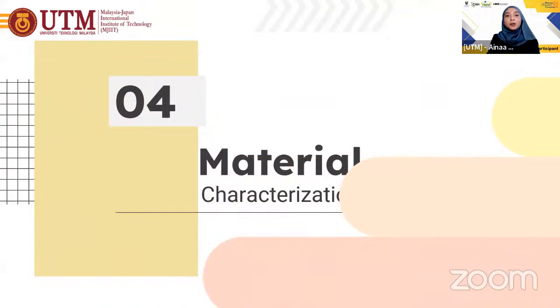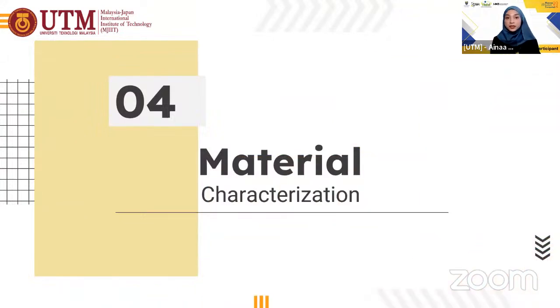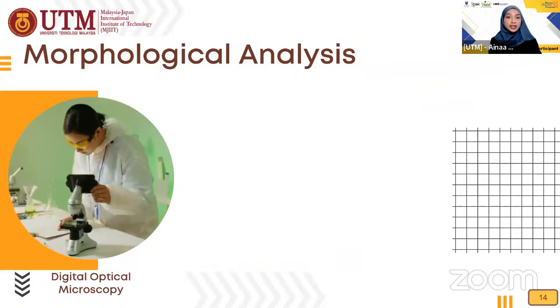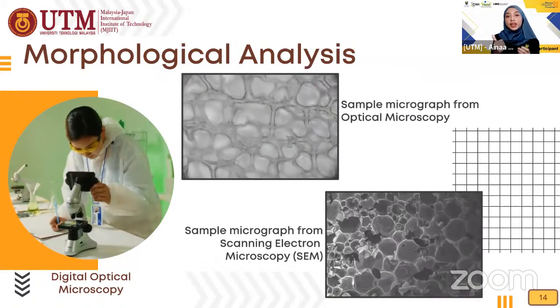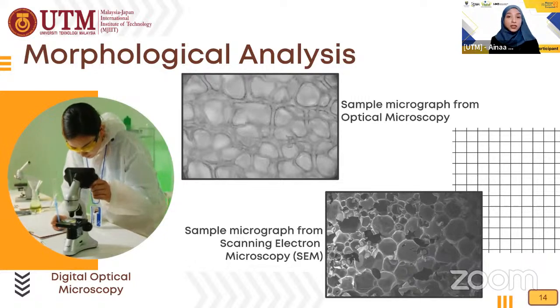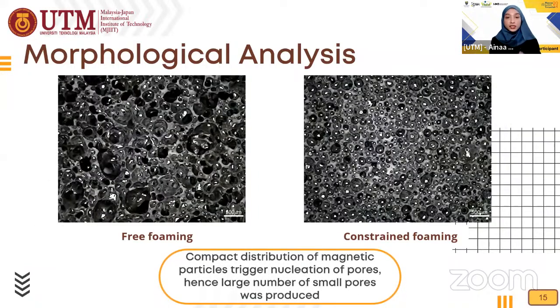Now, among various characterization processes available, there are two characterizations that are typically carried out for MR foam. First is the morphological analysis. It can be conducted using a scanning electron microscope or even a digital optical microscope. Based on a micrograph obtained by an optical microscope as shown here, MR foam fabricated with constrained foaming process, which is the micrograph on the right, has better structural properties with smaller size of pores as compared to the one fabricated by free foaming process as shown in the micrograph on the left.